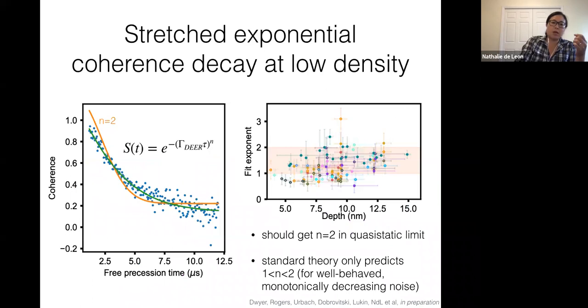The second puzzle was that a lot of this arose because I had an intern in my group who was very dutifully taking these measurements and doing a really careful job, but then he kept on bringing me fits to the data that just fundamentally didn't make sense from everything that I understood about spin resonance. Specifically, if you look up what you should get for a free induction decay in a quasi-static bath, you should get something that looks like e to the minus (gamma t) to the n, where n is 2.